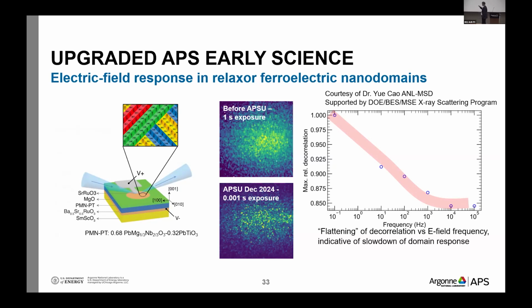This is XPCS. This is work by Yue Cao from the Materials Science Division, looking at polar nanodomains in a relaxor ferroelectric, where the key here is to measure the fluctuation of these nanodomains as you drive the system with an increasingly fast electric field, and to see how the nanodomains respond to this kind of excitation. And you see here an image of XPCS before the APS upgrade, with a 1 second exposure. And what you see here is the same type of material with a 1 millisecond exposure. And you can see that the contrast of the speckle is actually much better in the new image than it is in the old one.